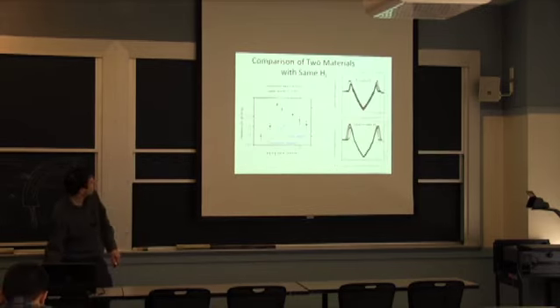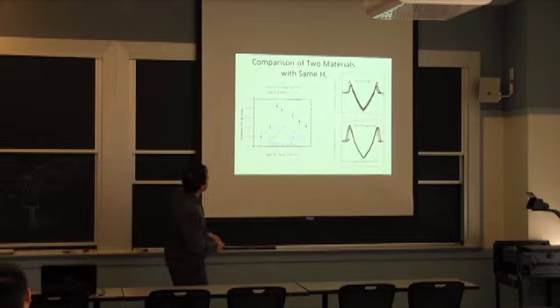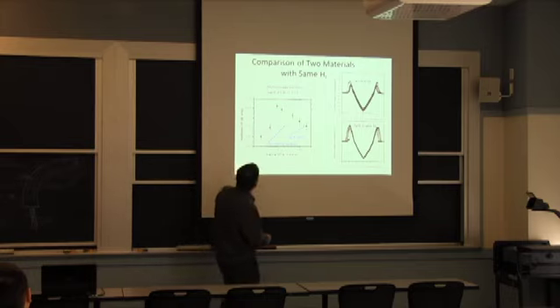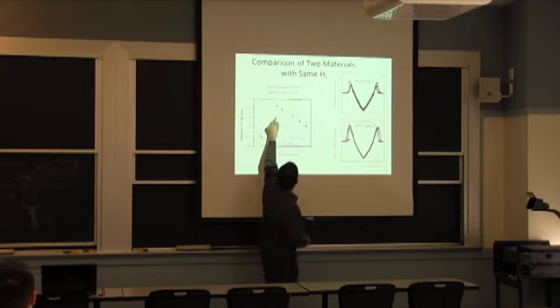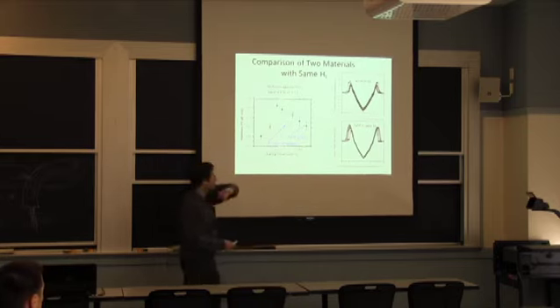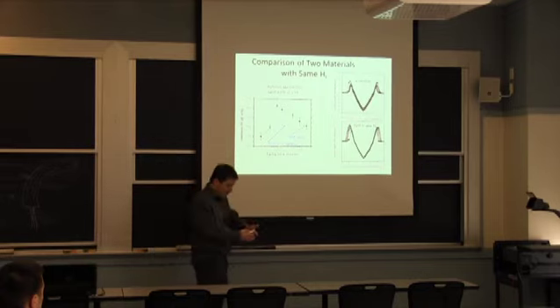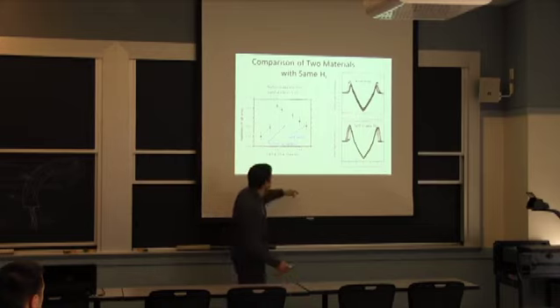And I have an example of that because I tested that in my thesis. This graph may actually be in my thesis. I don't know. This is essentially comparing the same plot of hardness as opposed to the aging time. I tested a material that was here against a material that was there, so before the peak and after the peak. And what we're looking at here is the profile of a scratch. So I came with a conical indenter, plowed into the surface, and made a scratch under a constant load for enough time to get a constant profile. So I imaged that profile.